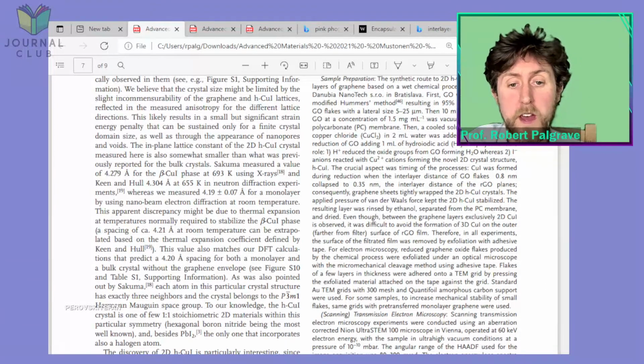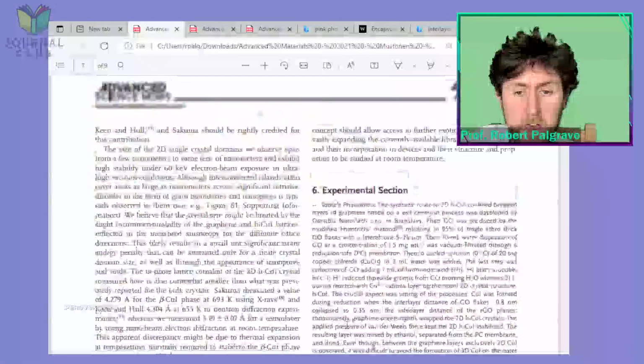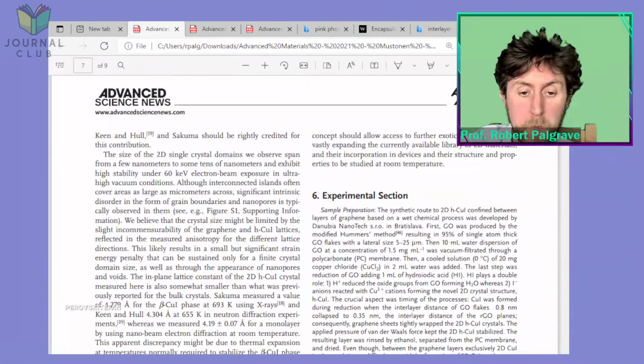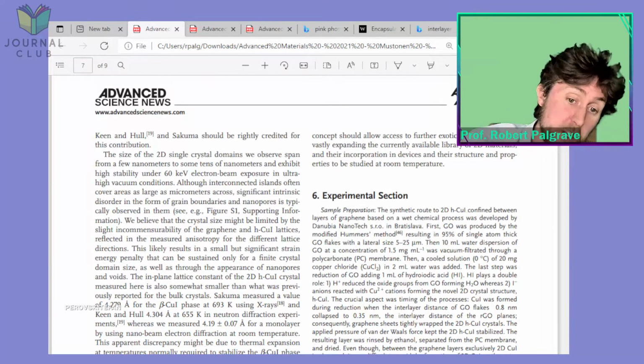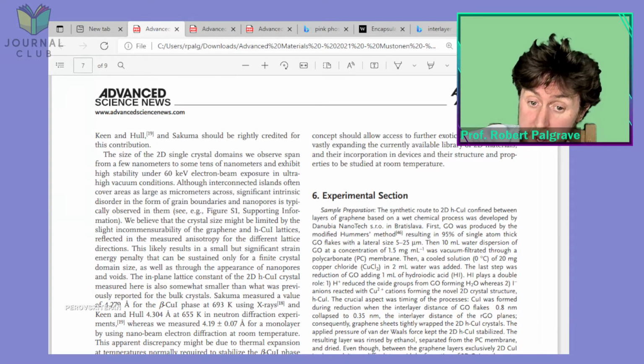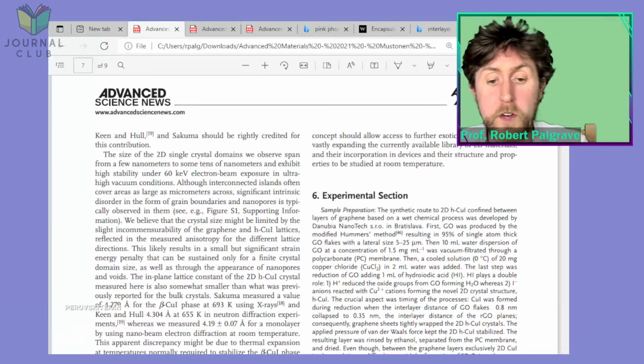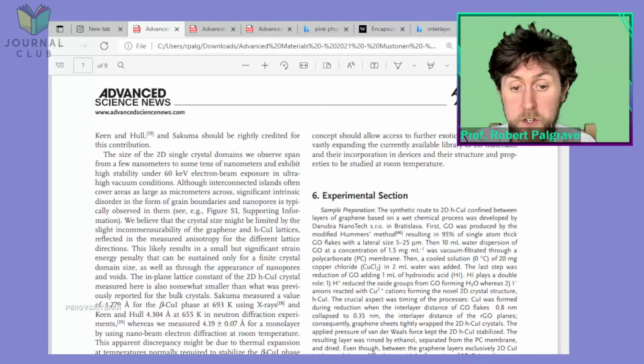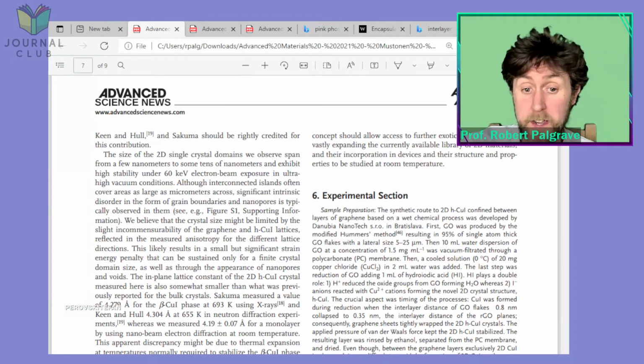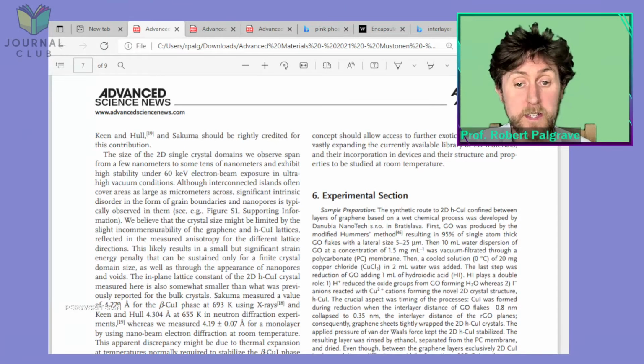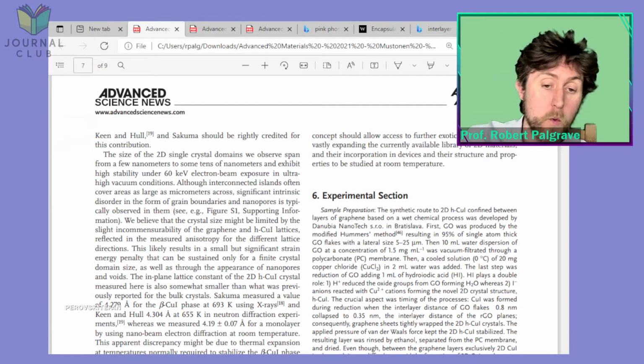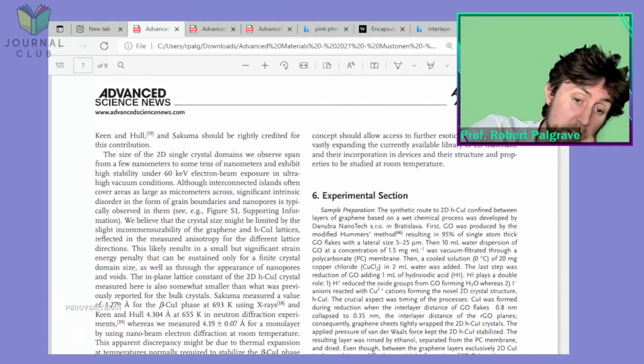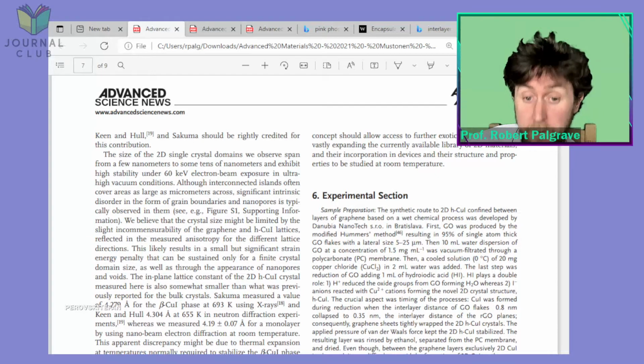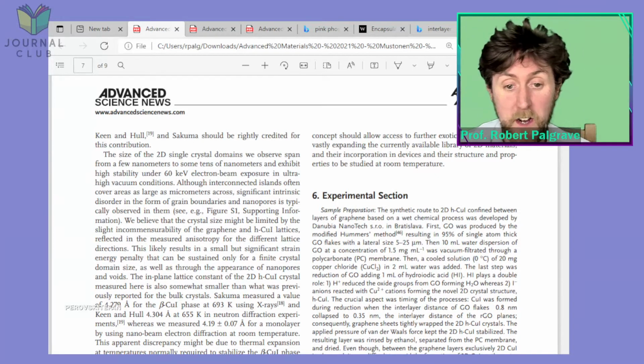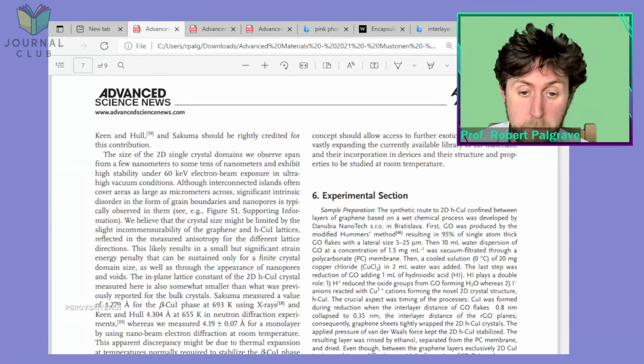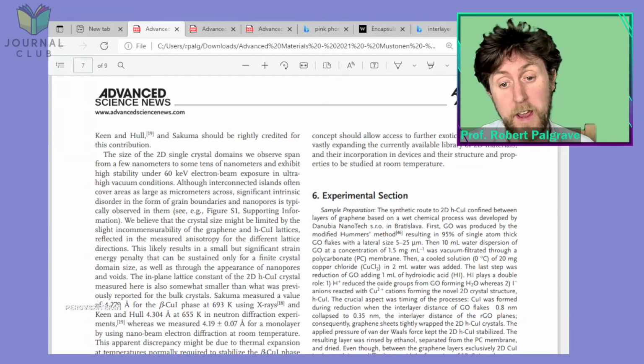So I think the most interesting idea here is that they're using the same method for reducing the graphene oxide, adding HI, and they're using that to also, at the same time, reduce the copper chloride CuCl2 to cuprous iodide CuI. And it seems like when they do those things at the same time, they end up with some of the cuprous iodide going between the layers of the graphite or the reduced graphene oxide and getting stuck there. And when it does get stuck there, as we'll see when we go further up the paper, it forms this other polymorph, this layered form.